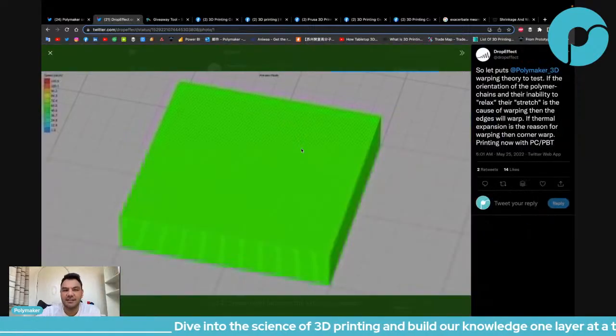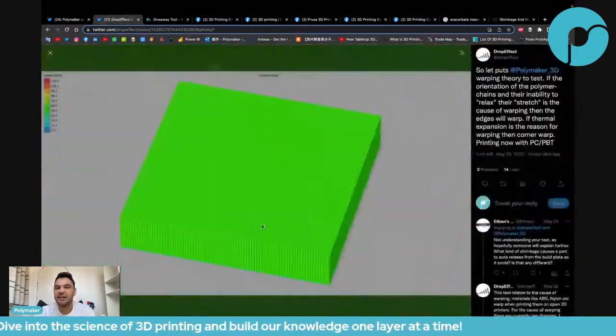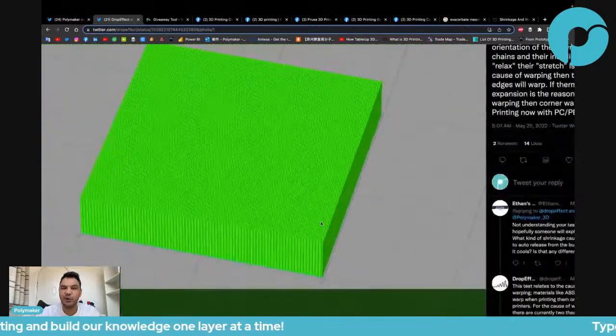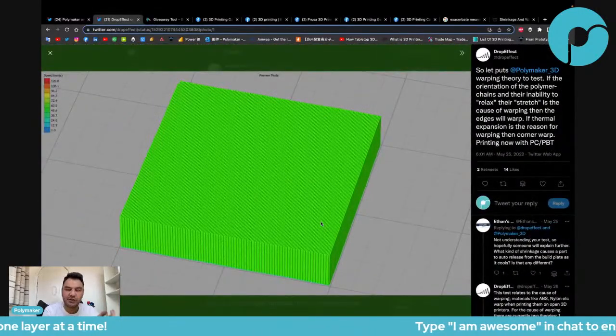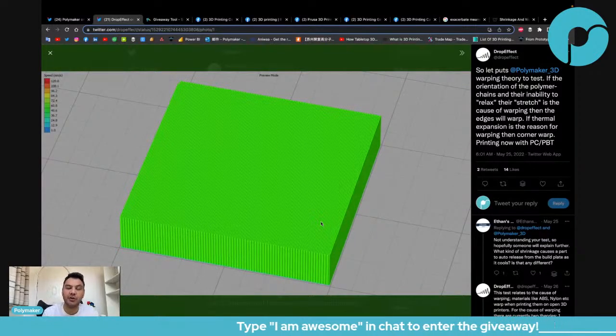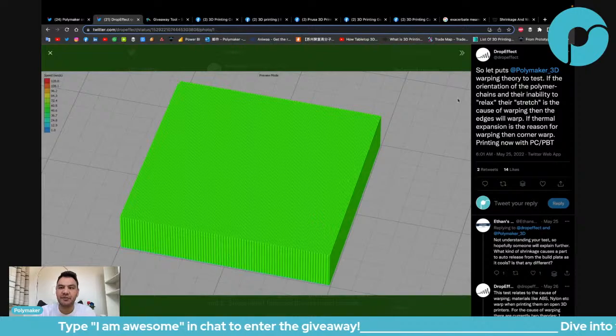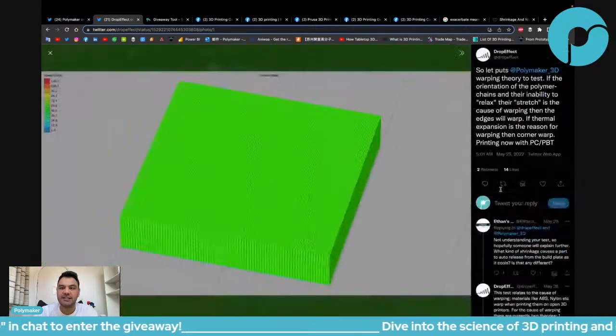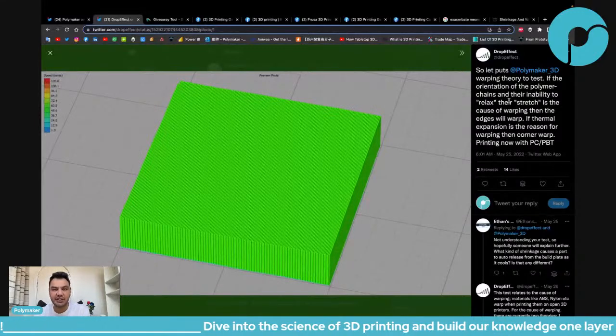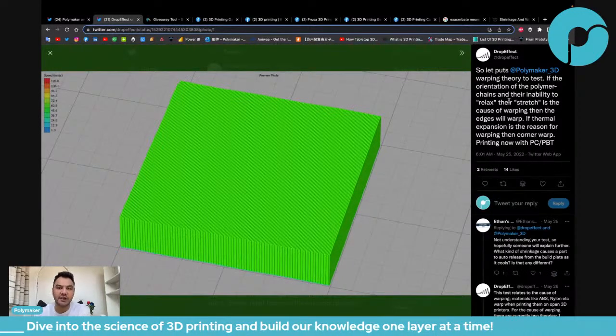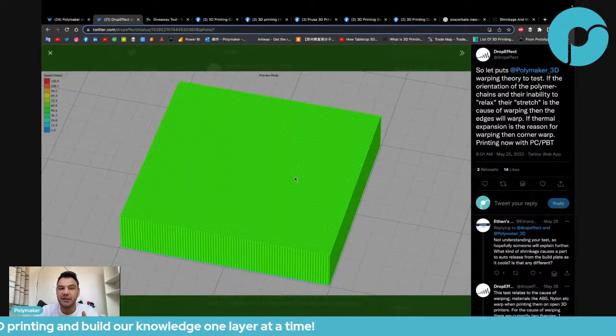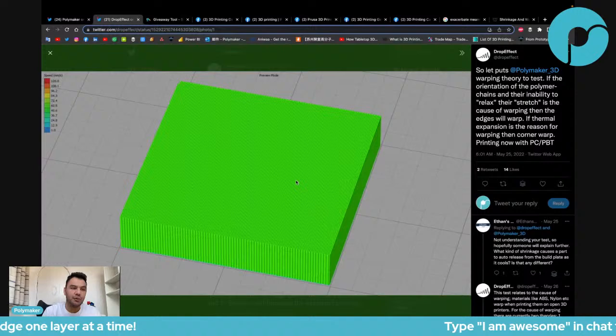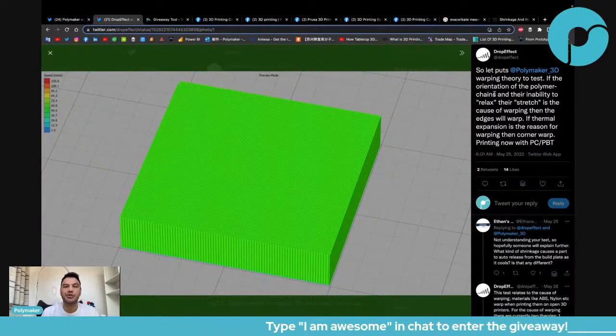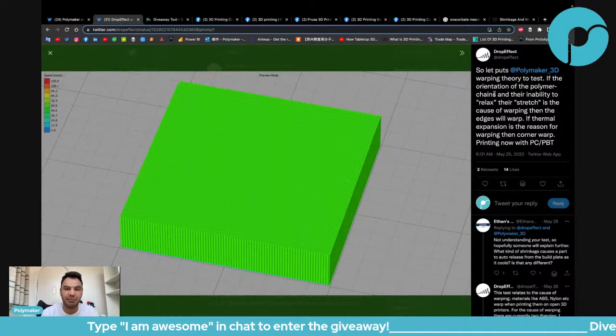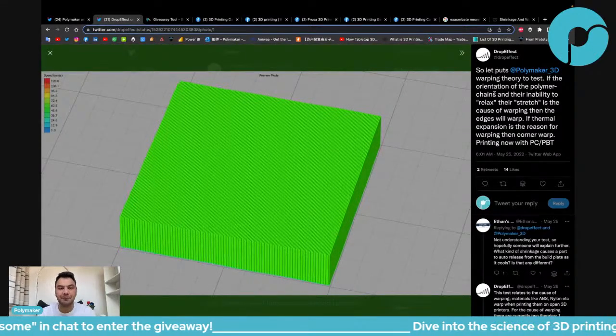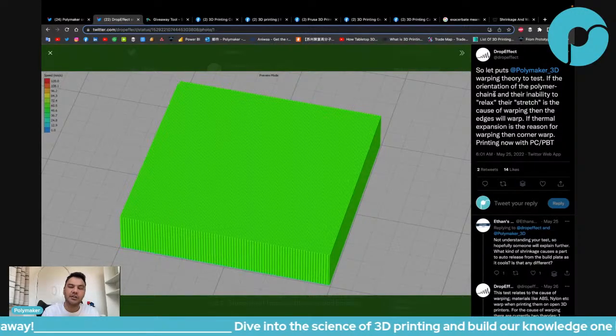Okay, this test, and basically what he was saying is that it will warp a different way depending on if it's elastic shrinkage or if it's thermal shrinkage. And it happened that it warped in a way that explained elastic shrinkage. That's how he confirmed, in his opinion, that elastic shrinkage is the main theory, the one I support, because of the orientation. So what he's saying is the thermal shrinkage is not really molecular orientation dependent. It's dependent on the temperature, but the elastic shrinkage depends on how the polymers are oriented.